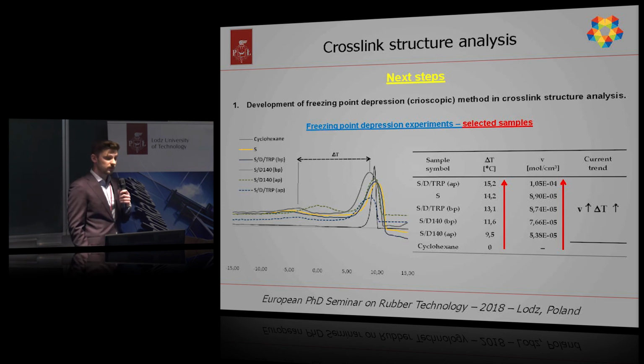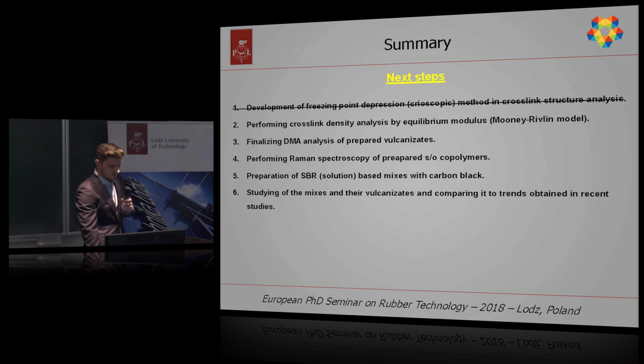So I think the trend is very positive, because when we have higher crosslink density, the crosslinks are located near each other. So the solvent is not able to crystallize, and it takes a long time to crystallize. So the temperature is moving to lower values. So the delta T is higher. I'd also like to perform a crosslink density analysis by equilibrium modulus and then calculate it from the Mooney-Rivlin model.